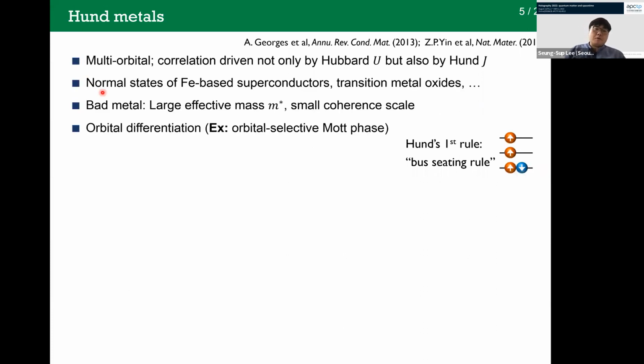Hund metals appear in the normal states of iron-based superconductors and many transition metal oxides and also many other correlated electronic systems. These are bad metals with large effective mass and also small coherence scale. And they exhibit orbital differentiation in that nearly degenerate orbitals can lead to largely different bands. An extreme example is the orbital-selective Mott phase. Here, some bands are insulating, Mott insulating, while the others are metallic, even though the orbital parameters, such as the orbital level positions, are almost the same.